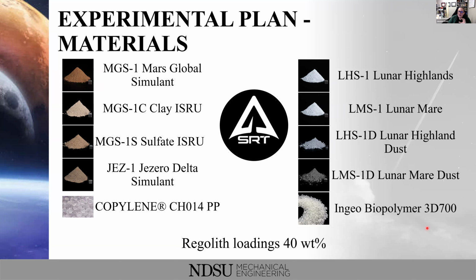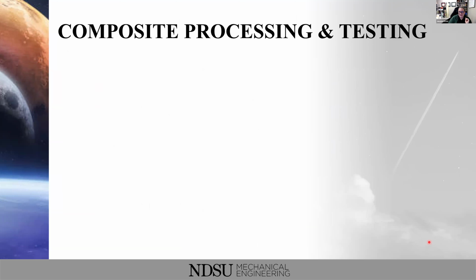It's a grade of PLA specifically designed for large area additive manufacturing, which is what we're doing with our big pellet fed printer from Re3D. In this case, we did studies all the way from 10 weight percent loading to 40 weight percent loading. We found that the mechanical property spread really didn't change a lot across 10 to 40 weight percent. And so we chose to move forward with the 40 weight percent regolith loading within our polymers to maximize the amount of regolith used and minimize the amount of polymer. I'll talk in a little bit about how we'd like to push that envelope even farther past the 40%.